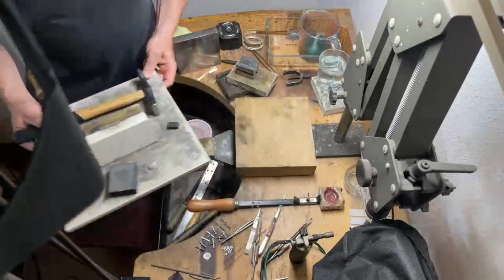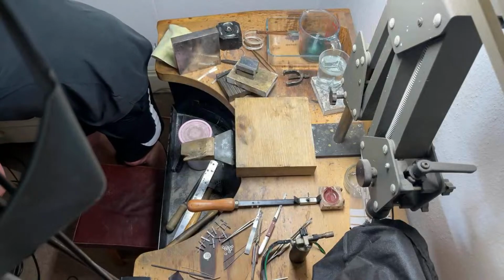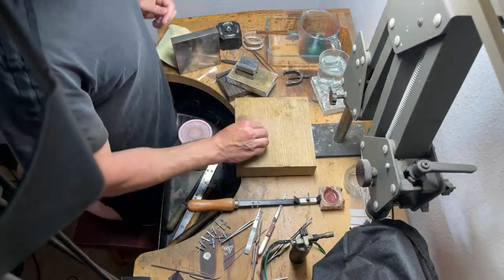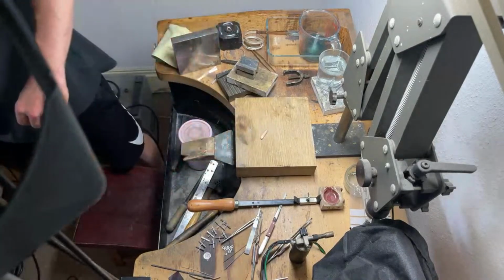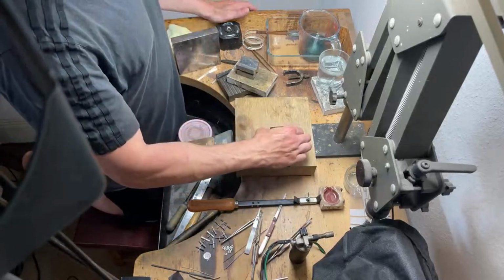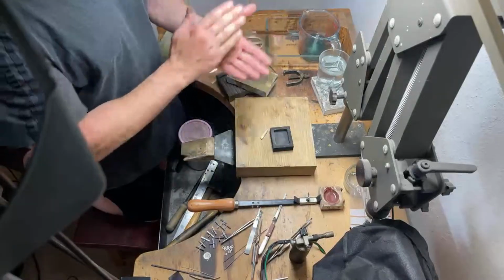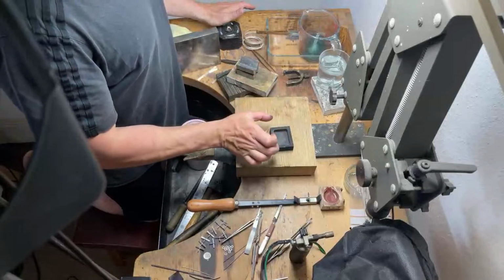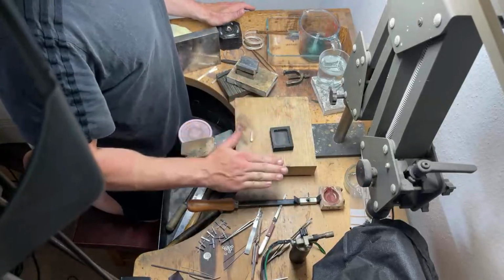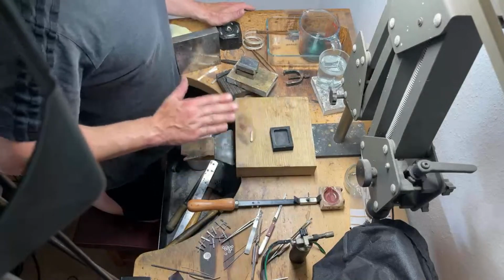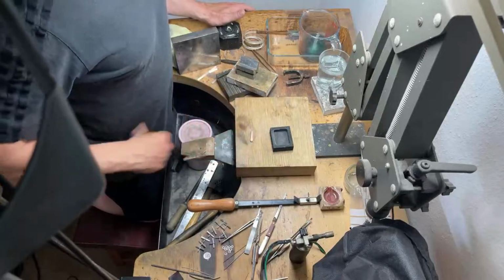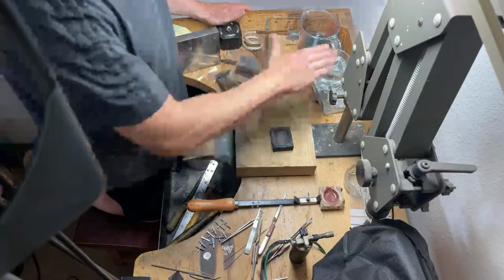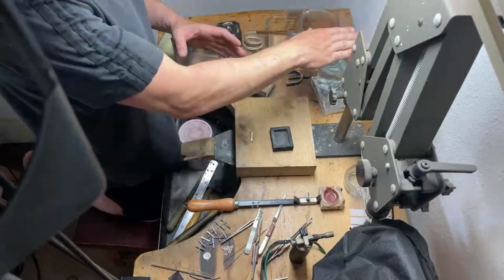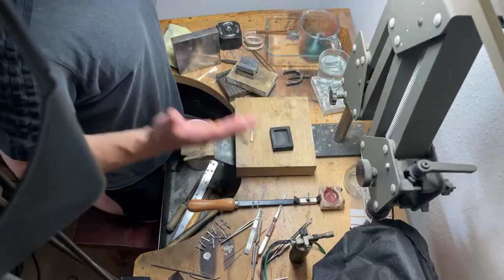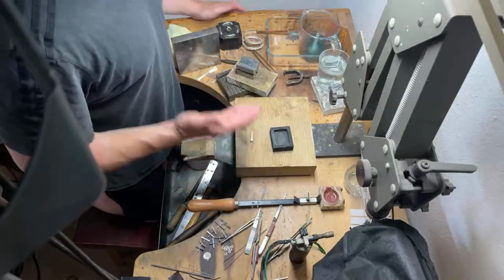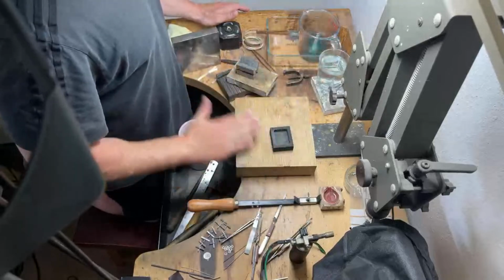So no books really cover the hand pouring process. There's no point asking bullion dealers, because they're doing it on an industrial process. I've seen one of our bullion dealers use a graphite ingot mould like this, but with a lid. They put the grain in it with the lid on, and then it goes through an industrial oven, a bit like the tractor fed pizza ovens a friend of mine used at the Pizza Hut over the road when we were kids. You put the pizza in one end and it was timed so it would come out the other end cooked. They have that oven, but obviously at 1,000 degrees. They roll the graphite with the precious metals in, and it comes out perfect.